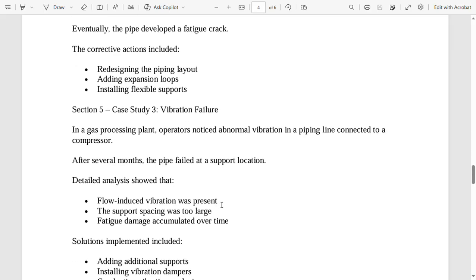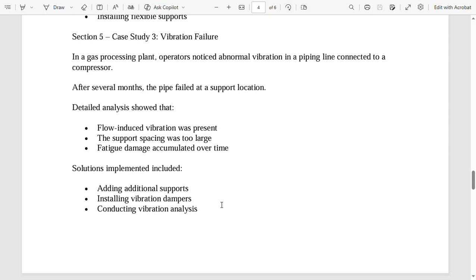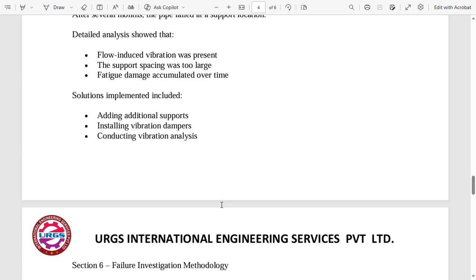Then the third case study is vibration failure. In a gas processing plant, operators noticed abnormal vibration in a piping line connected to a compressor. After several months, the pipe failed at a support location. Detailed analysis showed that flow-induced vibration was present, support spacing was too large, and fatigue damage accumulated over time. Solutions implemented included adding additional supports, installing vibration dampers, and conducting vibration analysis.